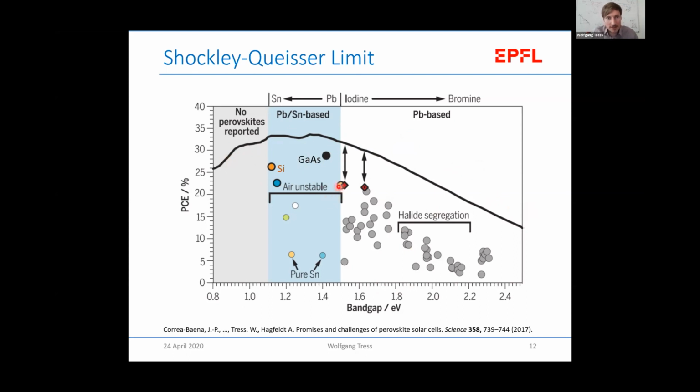And the perovskites, this is not completely up to date anymore actually. Like methylammonium lead iodide, formamidinium lead iodide, or a little bit of mixtures, they have band gaps in the range of 1.5 to 1.6 electron volt. So already rather well suited because you can reach efficiency values in the order of 30%. The newest value I was just showing you in this NREL chart is already at 25%. So there's a little bit of room still, but it's also already really close.